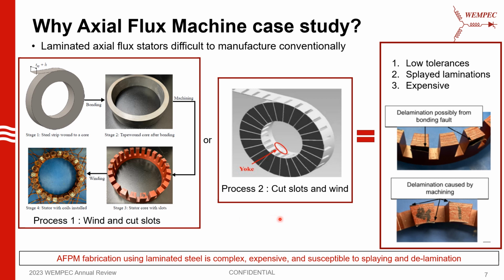And during our experience, we found that there are pretty much two processes with which you can build axial flux machine laminated stators. The first process is to take a tape wound core and machine slots into it. And the second process is to stamp slots into steel strip and then wind them into a tape wound core. But the major problem with both these processes is the low tolerances that you could achieve, splayed laminations. So I can show you the stator if you visit my poster later. You can see that the laminations can get splayed, and this is also very expensive to build.